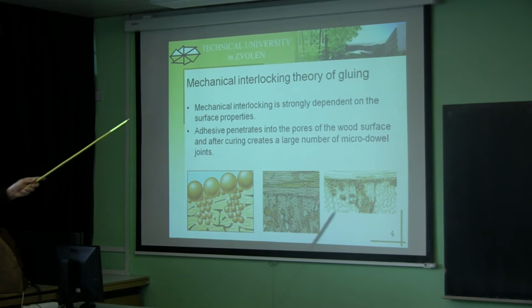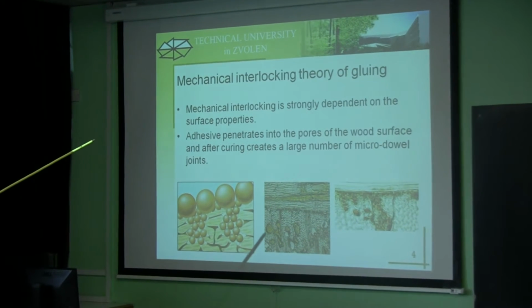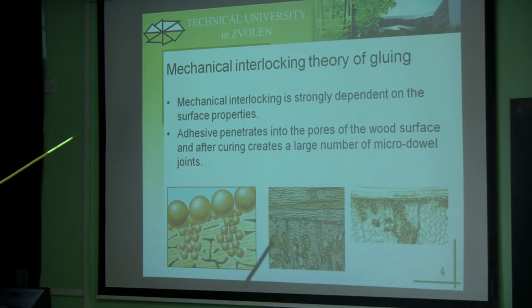On these samples, which are real samples from microscopy, we can see penetration of phenol formaldehyde adhesive, which has a dark color, inside the fibers. This is plywood, so this part is cross cutting, and the upper part is longitudinal cutting. Also we can see the adhesive inside the cut pores or inside the cross-cut pores. Another very similar picture is here. Also here is the cross section, and here is the longitudinal section, and we can also see phenol formaldehyde adhesive inside the cut pores. This is the mechanical theory of gluing.